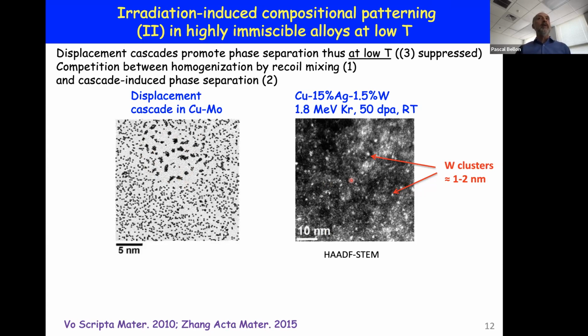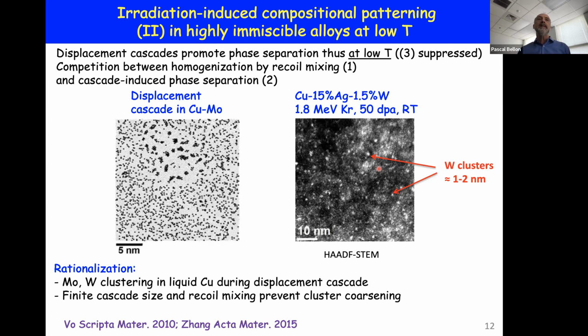And on the right-hand side is the experiment showing that, again, just by irradiation at room temperature, a temperature where there's no diffusion of silver, with this other mechanism we can trigger the precipitation of very small clusters, 1 to 2 nanometers in diameter. And those are extremely stable because tungsten or molybdenum are refractory metals with very, very low diffusivity in copper. So here we have a second way to tailor or structure the microstructure with a high density of very small precipitates that will be stable under radiation, and in some cases even under annealing at very high